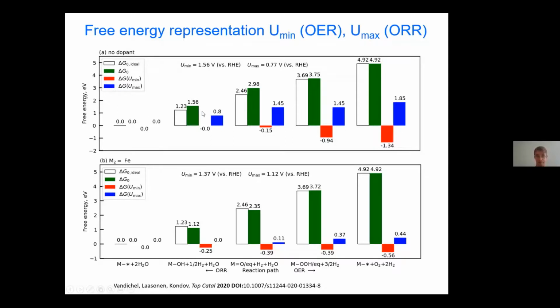So then we see in red, for example, the red bars, which reactions are rate determining in the OER process. It's not the reaction from here to here. It's not the reaction from the metal oxo to the metal OOH. It's the first reaction that is rate determining within the OER process. So at least with no dopant. If we have a dopant in the best position, M2, then it will be the attack of water to the metal oxo that will be rate determining. So then this step becomes zero if we fill in U-min.